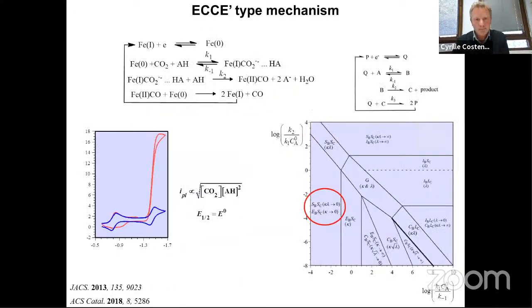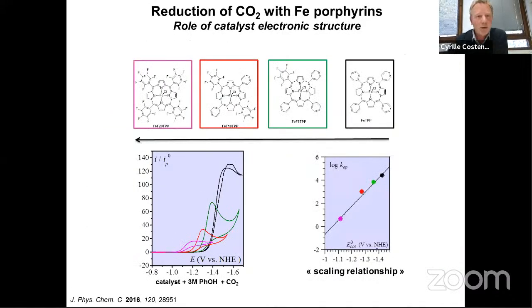Now that we have in mind the mechanism, the question is, what if we modify the porphyrin? And the way you can modify this porphyrin is to introduce substituents that will change the standard potential of the porphyrin. For example, if you put electron withdrawing groups, you will of course stabilize the iron 0 by delocalizing the charge onto the porphyrin, and you will make the iron 0 porphyrin less reactive. And this is actually what you observe by putting those electron withdrawing groups. You go in that direction, you get the standard potential more and more positive, okay? And as you can see, the catalytic current is decreasing.